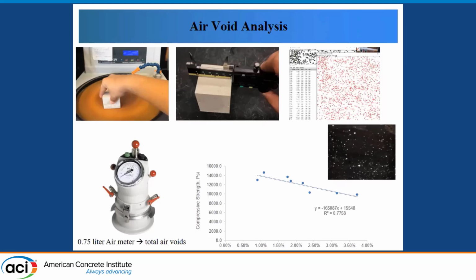Then followed by the digital photo analysis. Then the air voids have been linked to the compressive strength and found out that there is a linear correlation between compressive strength of the mixes with different air content.